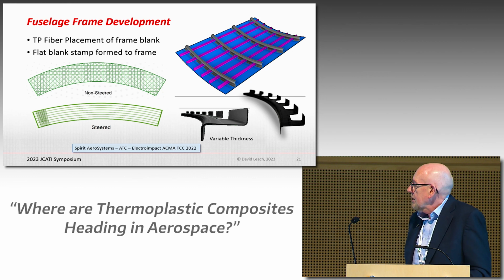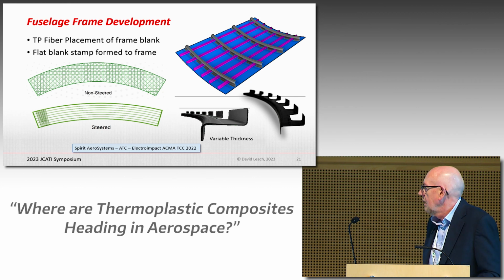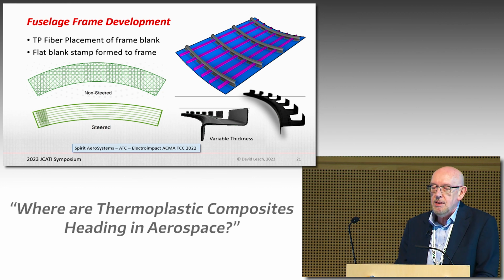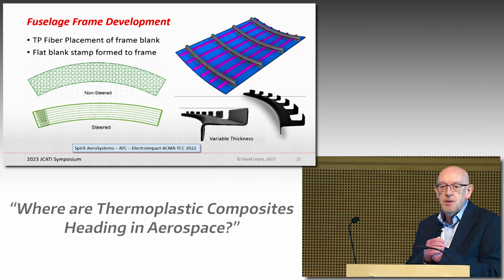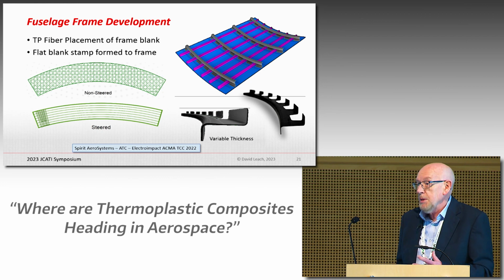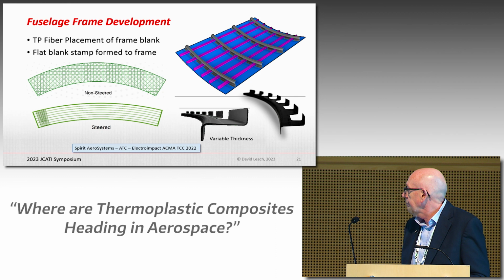So Electro-Impact actually made flat blanks, but with the steered plies, which at ATC we then took and stamp formed into the finished part. So this is actually the finished part. This is the model. This is the finished part here. Obviously, the geometric tolerancing on the outside of this has to be very precise as well, because that's mating directly to the fuselage. So your tolerances there are extremely tight. And so that's been part of the challenge of managing a lot of the thermal processes to really get very tight GD&T.